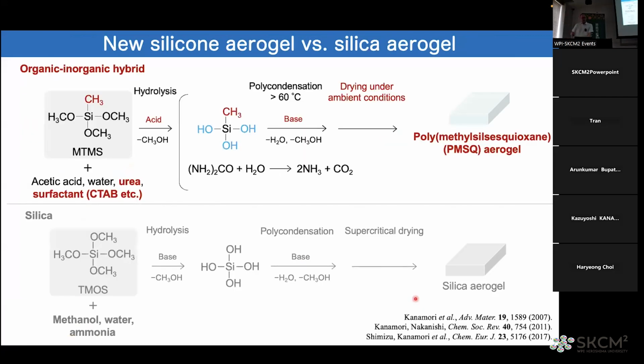So what we are trying is to make aerogels flexible, and make aerogels not from supercritical drying, but from ambient pressure drying. The difference is only one thing. In the standard silica aerogel process, people use a tetra-functional alkoxysilane like TMOS or TEOS, but we use a tri-functional alkoxysilane with one methyl group. The methyl group doesn't react in the course of gelation and drying. So we can prepare a lower cross-linking density, flexible material with a hydrophobic group from this precursor.